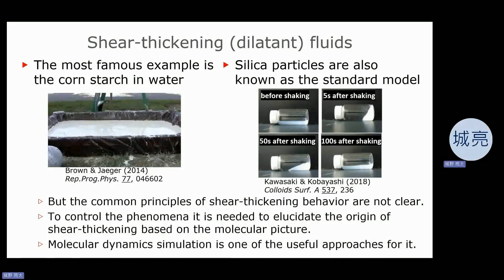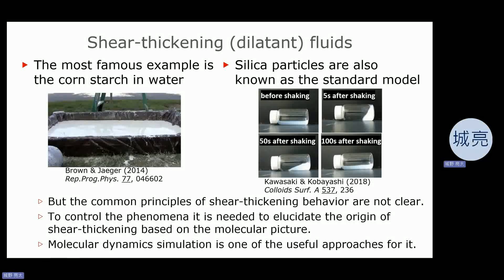The movie shows running on the mixture of water and cornstarch. For scientific research, rigid hard spheres in Newtonian fluid, such as silica nanoparticles in polyethylene glycol solution or micrometer-sized silica particles in alcohol, are used. The figure shows the behavior of suspension before and after shaking. The liquid-like behavior changes to the solid-like behavior after shaking, and it comes back after leaving. There are some examples showing the shear thickening behavior, but the common principles, especially the molecular level understanding of shear thickening, are not clear.